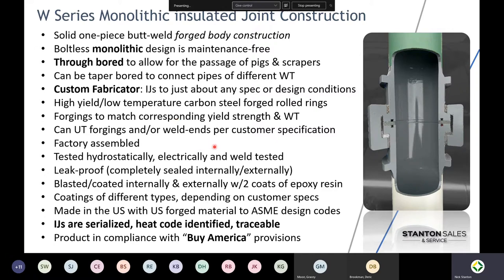We can UT the forgings or the weld ends for customer spec. They're factory assembled. Part of your data package is a hydrostatic test report. They're tested at 1.5 design pressure according to ASME code. They're electrically tested to 1,000 volts DC. We run across it. That's a resistance test that we give it. We also give it a withstand test. It's not a breakdown test. It's a non-destructive test, a test for current leakage. And we use 5,000 volts AC for the withstand test. And of course, it's well tested. So those documents become part of your data package. It's leak-proof. We, of course, blast it and coat it internally and externally with coating of your choice.